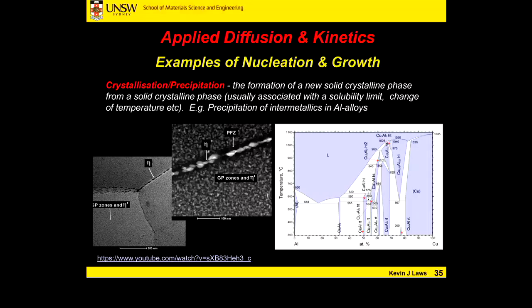Our new phase is dropping out of solution in the same way that the copper sulfate crystals were dropping out of solution as temperature was lowered. They're then forming at the grain boundaries. There's also a little bit higher mobility, or higher diffusion coefficient, at the grain boundaries because of that random crystal structure. So this one's really important for the strengthening of aluminium alloys.